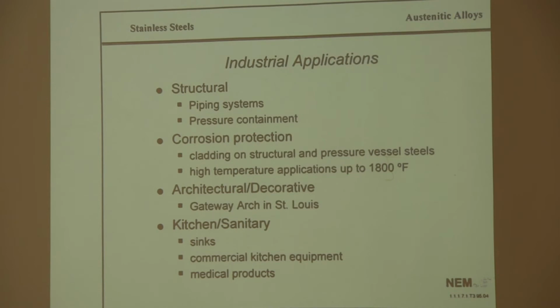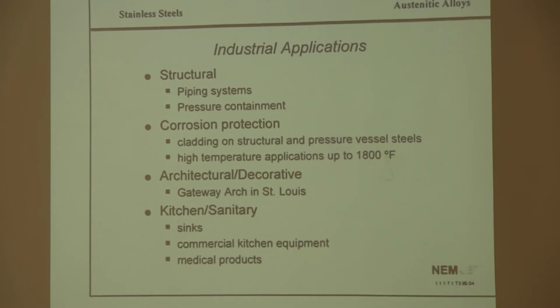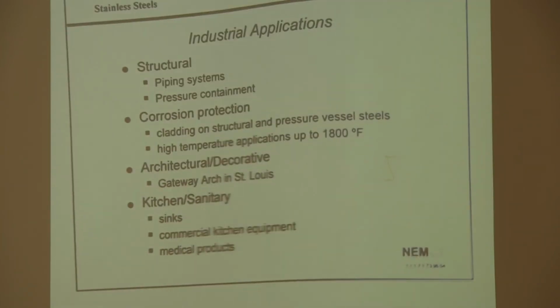One thing that it is good to mention is that the austenitic stainless steels are not suitable for chloride-containing environments or highly caustic environments, because those are the environments that do lead to stress corrosion cracking and intergranular corrosion and other types of corrosion with austenitic stainless steels.